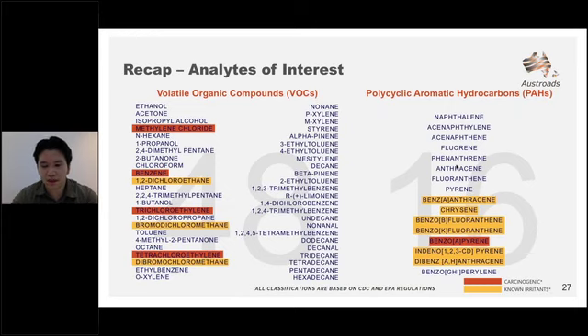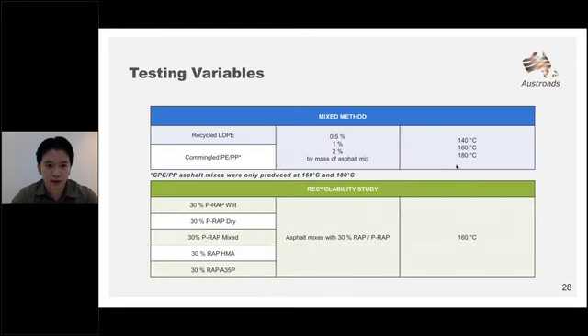A deeper analysis was conducted for each of these analytes to understand if using recycled plastics would either increase or decrease the possibility of these carcinogens. And as usual, a range of testing variable combinations were conducted for the mixed method. The plastic content ranged across 0.5%, 1%, and 2% by mass of the asphalt mix, while the working temperature ranged from 140, 160, and 180 degrees Celsius.